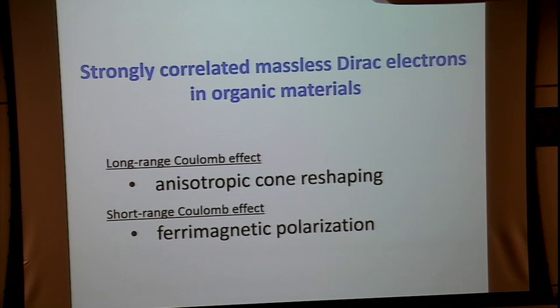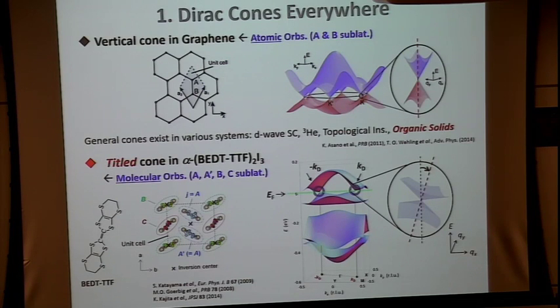And in the remaining time, I'd like to show you 2 experimental indications. One is the anisotropic cone reshaping due to the long-range Coulomb interactions. And the other one is the ferrimagnetic polarizations, very curious behaviors due to the short-range Coulomb interactions. Okay, this is a comparison of the very well-known graphene and this material. In graphene, the real space is a honeycomb lattice, very highly symmetric. Reflecting this symmetry, even in the K space, the Dirac cone is symmetrical, and the Dirac points are located on the very special point of the boundary in the K space.